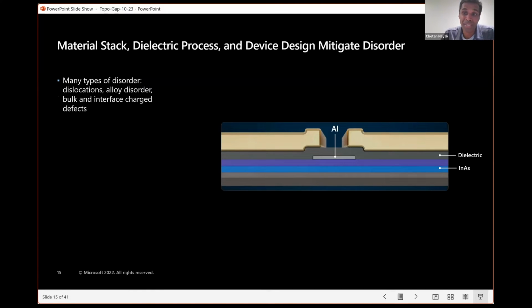Okay, so we need to keep the disorder low in order to have these regions of topological phase at all, since the localization length needs to be comparable to the clean system coherence length, or preferably longer. Now, there are many types of potential disorder in a system like this. There are dislocations, like screw dislocations, that might be coming from misfits in lattice constants between the different layers. There could be alloy disorder. There could be charge defects, both in the bulk and the interface.